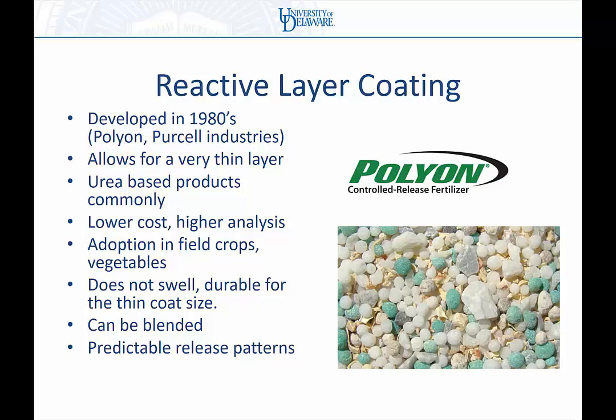They don't swell. They have really thin coatings, so the analysis is higher, 41 to 44, 45% nitrogen on coated urea. They can be blended. You still have to take some care with them, but as long as you're careful and put them in at the last part of a blend, it works just fine, and they have really good predictable release patterns.